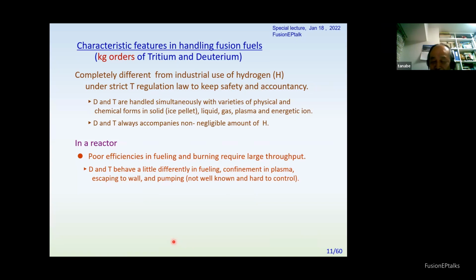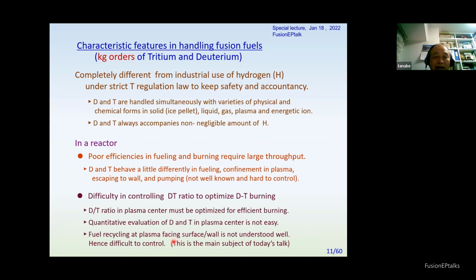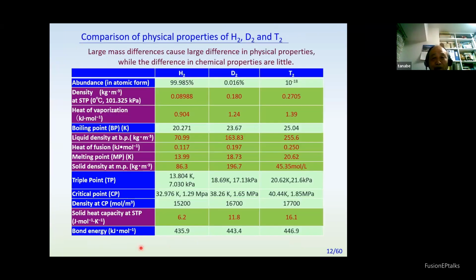So this is very large. And controlling DT, because they are mixed, should be done independently, to make the DT ratio optimized. It is necessary to evaluate D and T quantitatively, fueling of D and T separately. Fueling decided at the plasma surface is also not easy because of the mixing, so the response to the mixed plasma is not so easy to observe, and also to control.